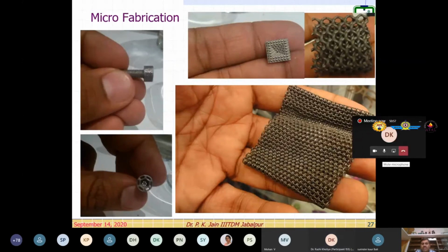And look at this, the titanium screw which we use for biomedical applications. Suppose we heard that a rod was put in the leg or a new bio implant was inserted. For tightening, we use this kind of titanium screws. And the requirement is that tissues should pass through these titanium screws, right? So you see the through holes in that. That is not possible with any other technology, even with wire EDM. You can see these horizontal holes are also through holes, right? These are interconnected pores so that tissues can pass through. That's the requirement. So it's certainly a different setup if we talk about biomedical.